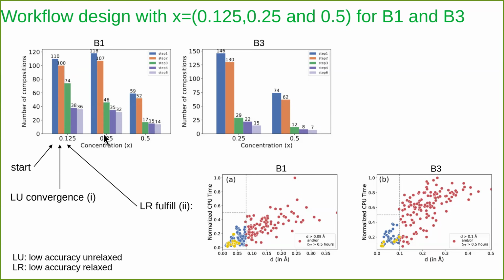Then we take those where you have a certain selected displacement inside the atomic relaxation. You see that the biggest drop actually happens here. Almost half of them have too big relaxations, and we throw them away, and only 36 at the end will go into the final stage to get the elastic constants. If you take a B3 structure, which is a more open type, then you see that it changes much more drastically: the atomic relaxations are bigger, and many more candidates are thrown away. That underlines how serious the computational issue is that we need to face here.